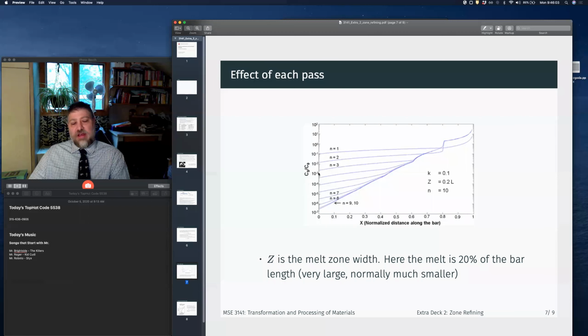So if we start out with metal that is 99% pure, and we're trying to get to 5 nines, because this is a log scale, if we replotted this as a linear scale, it would be like bing, and then we would just cut this end off, and everything down here is good. But in reality, we have multiple passes, we reach our saturation, we cut our bad stuff off, and then we can do zone refining from the other end to homogenize this out at some low value. And that's called zone leveling, which there's a homework question on, and I just gave you most of the answer to inadvertently.